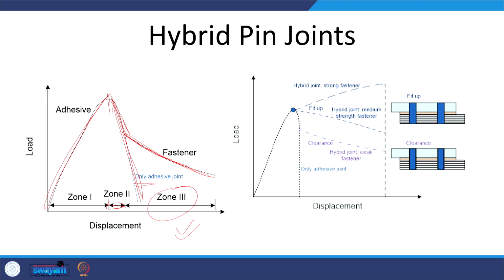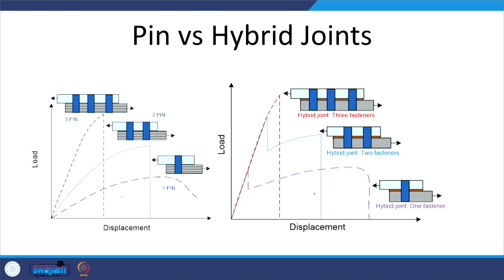So, what if there is no gap between the fastener and the sheets? What happens when the fit up is perfect between the sheets and the mechanical fastener is that as soon as the adhesive joint fails, the load is immediately taken by the mechanical fastener, since the fastener is strong. So, the load displacement curve comes out like this, and if the strength is a little less, it will be like this, and if there is a little slippage or clearance between the sheets, the load displacement curve will come down, and then the load will be taken by the relatively weak mechanical fastener. So, this is how we can get a variety of profiles as far as the adhesive joint clubbed with the mechanical fasteners is concerned.